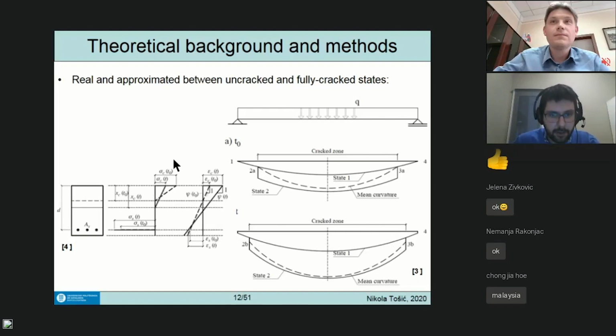So here, focusing back on the cross section, we should note a couple of things. First, this is the strain line at T0, and then there is an increase of the concrete strain, but a very slight increase of the steel strain, practically remaining constant. So basically the rotation of the strain line happens more or less around the reinforcement, and this is the increase in curvature due to creep and shrinkage.